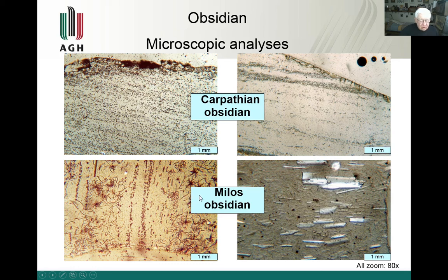In Milos there are a few kinds of obsidian. In one kind of obsidian, one can see iron inclusions. It's mostly hematite, and as you see, it's orientated. These inclusions are present in an orientated way, and because of the orientation of inclusions, the best way of knapping is parallel to this internal structure, to the presence of these internal inclusions.